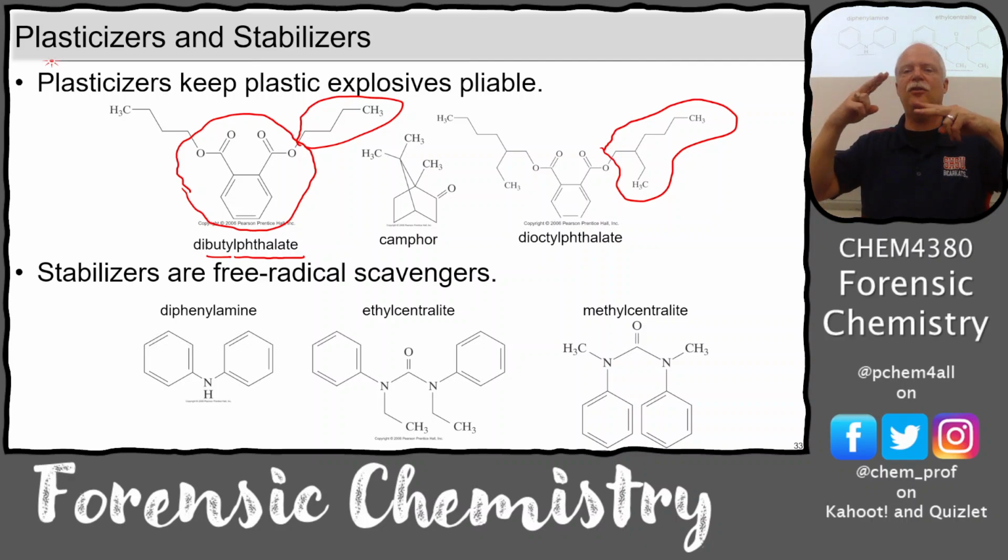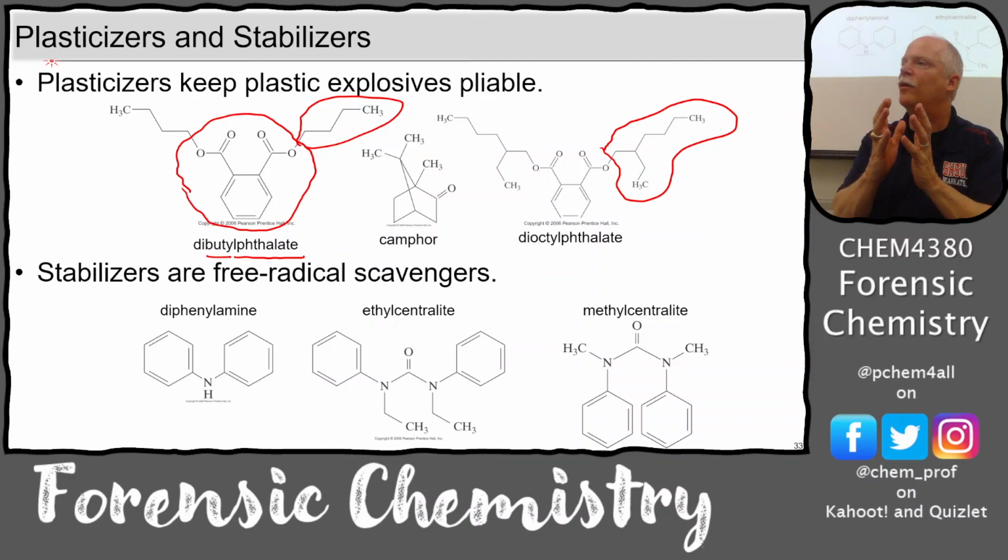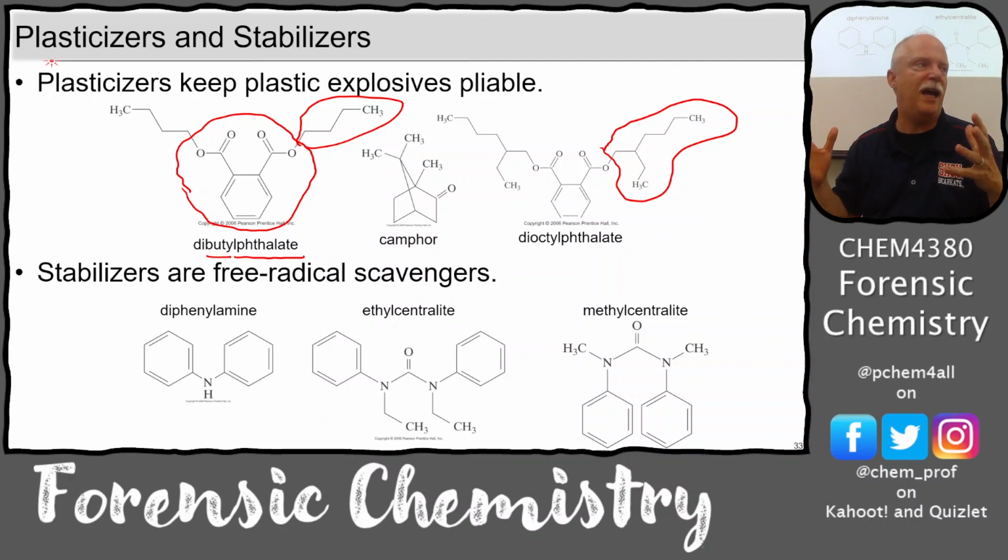You got the CH2 groups that are bumping around. They're not lined up, but over time, they start to line up. And you get two or three together, and then the fourth and fifth, it's easier and easier to get them to crystallize. That forms a hard domain in that polymer. And then when there's stress, the hard domain stays put, and it rips the polymer around those hard domains. Okay. So we don't want that to happen with a lot of our polymers. We want them to remain plastic and movable. So we put plasticizers in them.